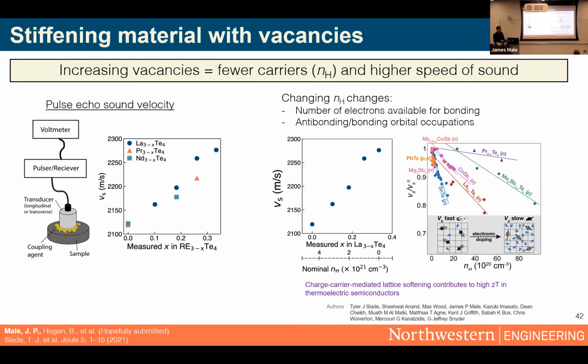So remember, as we add vacancies, we're also removing electrons from our structure. So that means higher X vacancies are really similar to being a low doped semiconductor material. We actually recently published this paper showing that high carrier concentrations in thermoelectric materials can lead to softening of sound velocity, which is likely due to essentially those extra carriers affecting bonding, occupying antibonding orbitals, et cetera. And I thought this is a very fitting paper for today because every member of the committee is listed as a PI. So this is a great room of collaboration here. But anyway, so that's what we believe is happening here. The effect of charge carrier softening is stronger than the effect of removing those cations.